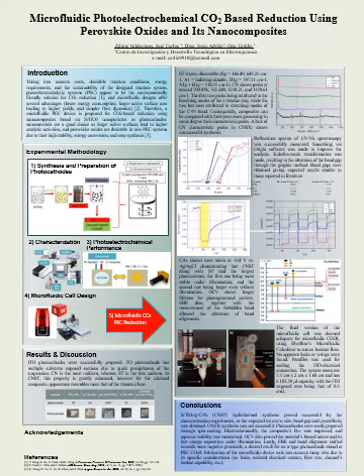Also, we can observe the chronoamperometry, with no light and with interrupted light irradiation, in order to observe electrical current and photoelectrical current. In this case, we can observe that the composite shows great photocurrent stability, shows a high value of photocurrent, and well, is the highest along with its precursor of strontium titanate, which is desired for the microfluidic CO2 reduction process.